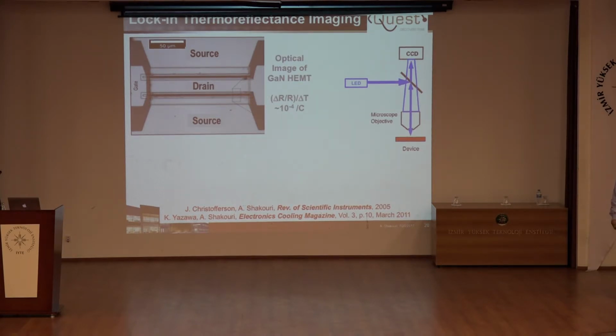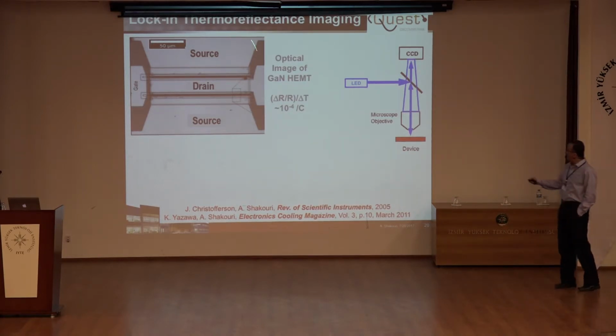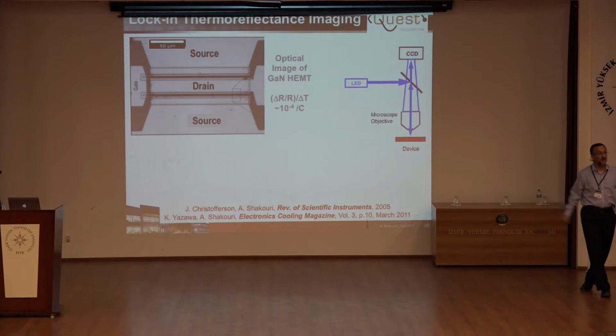The reflection coefficient of every material is a function of temperature. So you can use what you see by your eye as a thermometer. But the effect is small. For every 1 degree temperature change, the reflection coefficient changes 1 part in 10,000 to 1 part in 100,000. So if this device is off, all of it will be the same temperature. If the device is on, for example, the metal here could be 30 degrees hotter than here. 30 degrees means 30 times 10 to the minus 4 change in reflection. Can your eye see such a small change? No. Can any camera see such a small change? No. But how do we measure small signals?